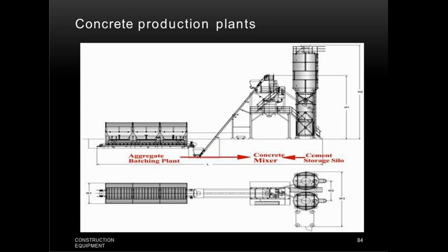This fully and partially mixed concrete is transported in the truck, and mixing may take place also during the transportation. The mixed concrete is kept in a plastic state and saved from segregation through the continuous agitation of the drum. The usual speed of the drum is 2 to 6 revolutions per minute, and a water tank is fitted on the truck to supply mixing or cleaning water to the drum.